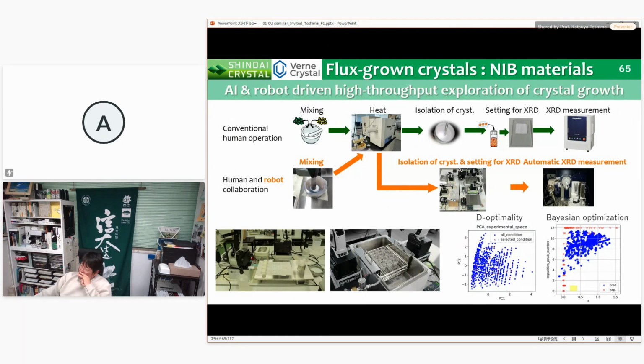Flux was used to create low aspect ratio crystals. Usually, experiments done by humans require mixing, heating, crystal isolation, and phase identification, which takes time. Therefore, this time we attempted high throughput experiments by introducing a robot into part of the processes. Specifically, we automated the mixing process and crystal isolation phase identification preparation.